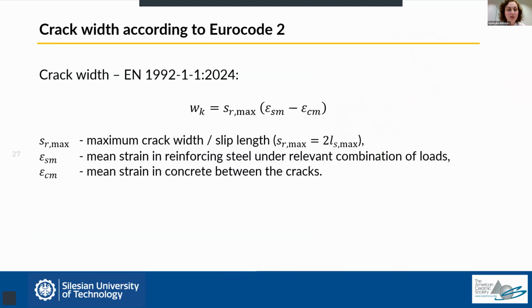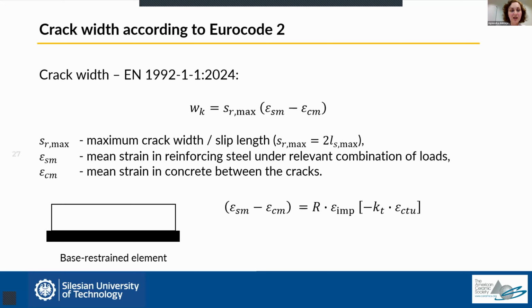According to Eurocode 2, which is the Eurocode dedicated to concrete structures, the width of the crack in general, not only the crack which is caused by imposed deformations, can be calculated as a product of crack spacing and the difference in mean strains between steel and concrete. Nonetheless, in case of restrained cracking, as I showed you, we don't have full restraint of the element, which means the width of the crack will depend not only on the applied reinforcement, but on the magnitude of restrained deformation. That is why the standard proposes to calculate the mean strain difference as being dependent on this restrained part of strain. So this way we take into account the local effect of the crack on the element.